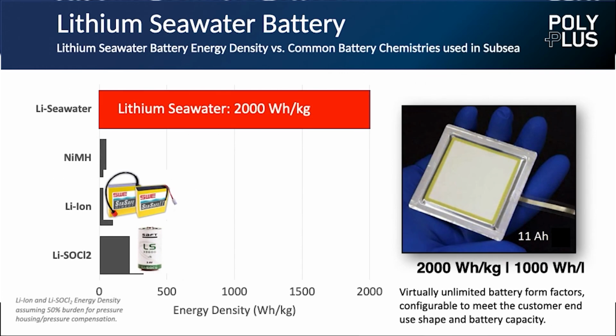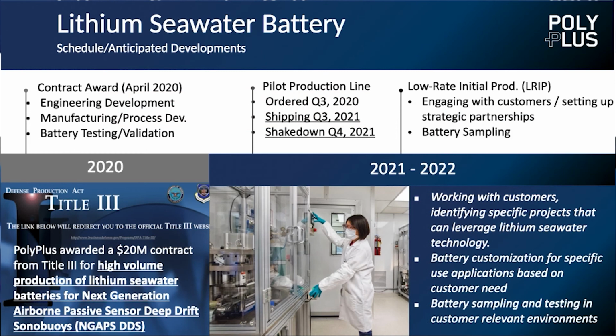If you look at the other batteries that have been used in deep ocean, they have to be protected from pressure, so their energy densities are vastly derated. Of course, ours are not. They're not even close. Lithium seawater, as I mentioned, has already demonstrated upwards of 2,000 watt-hour per kilogram and 1,000 watt-hour per liter, and we can probably push that a bit higher. So that is going to go commercial.